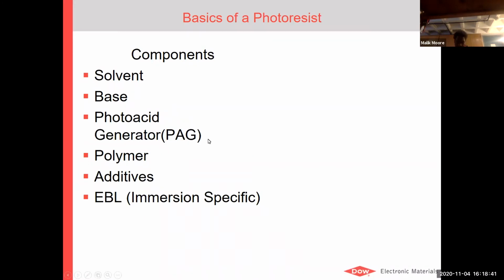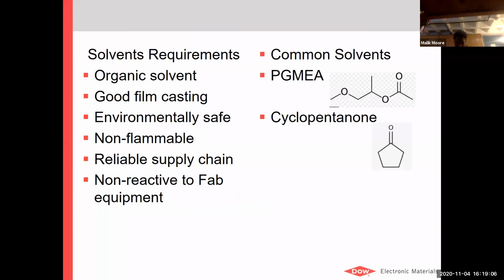You have a very specific polymer that's built to react to the PAG. And then you have additives that adjust your film properties, and very specific to immersion is an embedded barrier layer, an EBL. What this does is it self-segregates to the surface, making an internal protective coating and adjusting the water contact angle. And this is a very cool set of chemistry that's there.